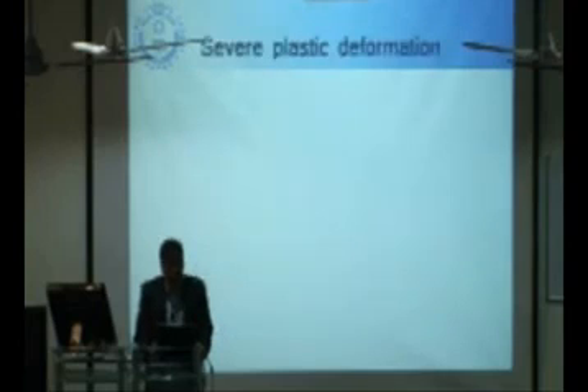What we are trying to do is severe plastic deformation. Already in many of our devices and in metal forming industries, we use plastic deformation. The problem with plastic deformation is that a change in shape takes place. So we have a limitation in applying plastic deformation to the material. Here we come to the severe: if we can severely deform the material, we can change the microstructure. SPD refines grains by introducing a large number of dislocations that arrange themselves to produce ultra-fine grains having high angle grain boundaries.